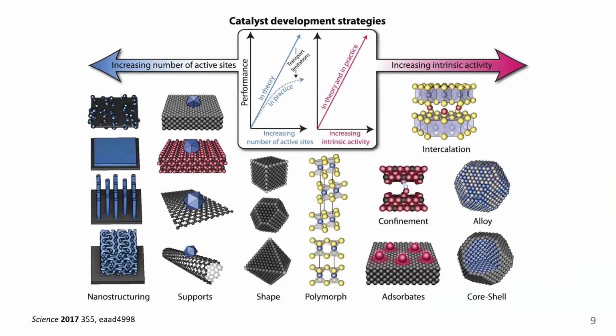And so there's a vast number of approaches to engineering electrocatalysts. A lot of the work that has been done to date is related to nanostructuring, which can change the activity by increasing the number of active sites. Essentially, we get more reactions per given volume, per given area, and so that increases the activity. However, that has a limitation, and moving forward to really improve the intrinsic activity of materials, we need to explore more advanced, more sophisticated methodologies such as alloying.